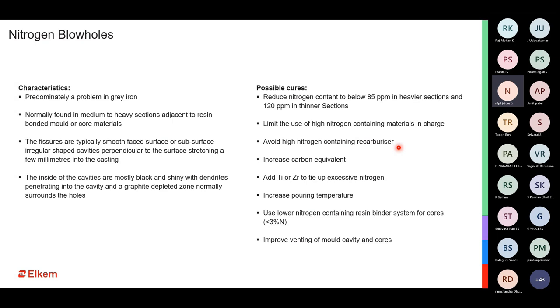Thereby, there can be all other ways of doing it. Like I mentioned, how do we control the incoming nitrogen into the system? By using binders and resin systems which do not have enough nitrogen, and also by ensuring that we have sufficient vents so that whatever nitrogen does come into the system is allowed a free path to escape out of the cavity.